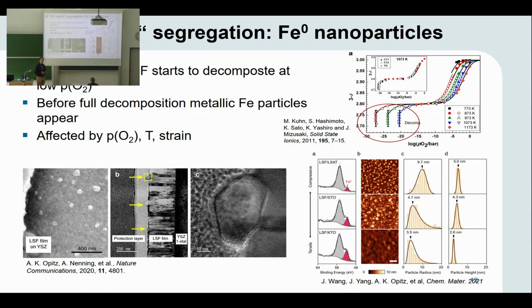However, not all cation segregation phenomena are bad. There are also positive segregation phenomena, especially in reducing conditions, where metallic iron particles appear on the surface. And this metallic iron is anchored into the oxide. So you can see here that this is the oxide, and the particle is inside the oxide due to this segregation and exsolution process. And this makes it morphologically much more stable compared to an impregnated nanoparticle.